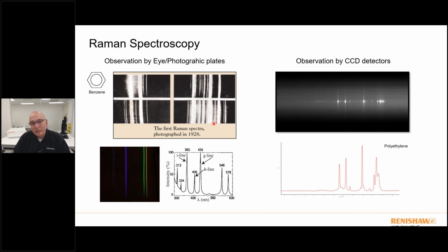And then that sample, benzene, was illuminated by the light. And so what you're seeing in this top left photograph is that dispersion caused by the prism without any sample. And then you introduce the sample and you start to see these additional bands showing up. And I think what you're seeing is just multiple Raman features based off of the multiple excitation lines here. But I can clearly see that there's two bands here.